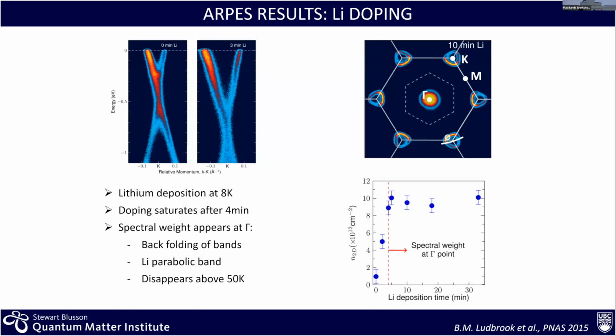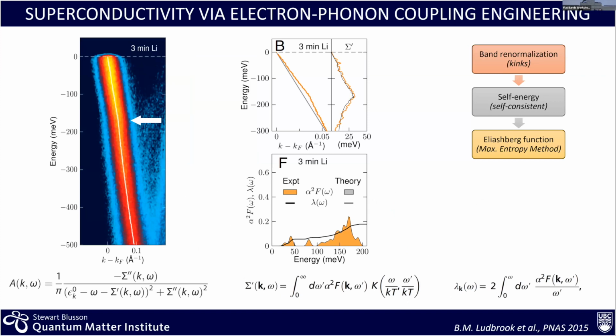Together with the enhancement or enlargement of the Fermi surface, we also get a folding of bands at the gamma point and also a lithium band in this particular case of heavy doping. And I'll come back to that towards the end of the talk. Now, the question is, what can we say about electron-phonon coupling?